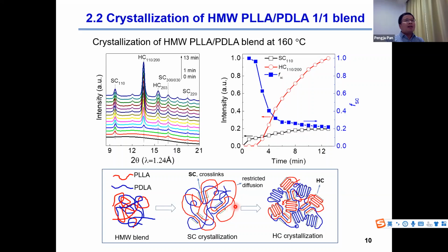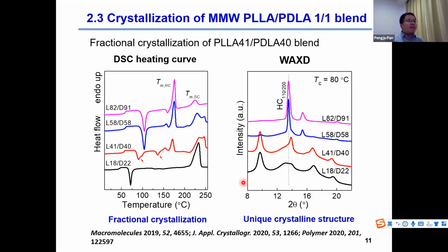We expect that if we can increase the content of stereocomplex, it will have a more significant effect on the following homocrystallization process. So it can also induce the formation of some specific homocrystalline structure. And this was confirmed in the medium molecular weight blend. The molecular weight of PLA and PDLA in the medium molecular weight blend is about 40,000. The medium molecular weight blend sample shows very special crystallization kinetics and crystalline structure.